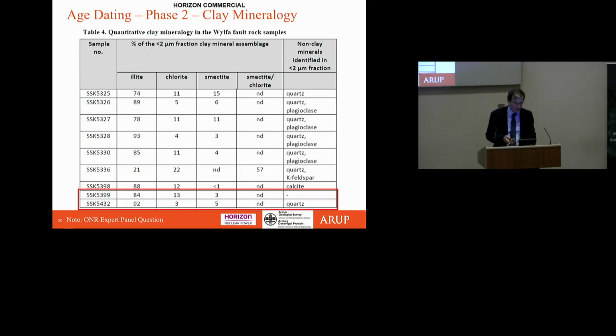The eagle-eyed amongst you will notice that there was one sample that had a low amount of illite in it and a larger amount of smectite clay. And smectite is not suitable for doing potassium-argon dating because it's an interlayered clay and you can't separate out the bit that's got the higher potassium in it. It's mixed and it gives you very difficult to interpret results. And we made a critical error at this stage, and we chose not to do age dating of that sample. And we went off and did the dating on all the other samples, and it proved to be quite problematic, which I'll describe a bit later.